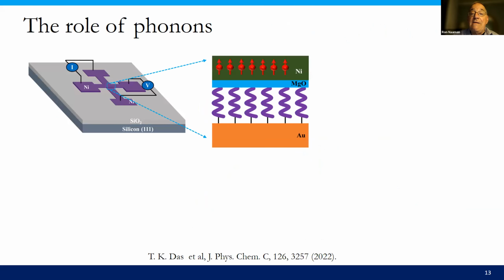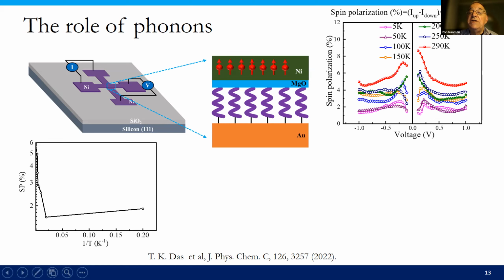And what is the evidence for this? So here's an example where we put chiral molecules in a sandwich configuration between gold, a layer of magnesium oxide to avoid pinholes, and then a nickel layer that can be magnetized either up or down. And by switching, we measure the current going through the system when the magnet is pointing in one direction and the opposite direction, and as a result, we get the spin polarization, which is defined as the current going up minus the current going down over the sum of them. And we measure it as a function of temperature.